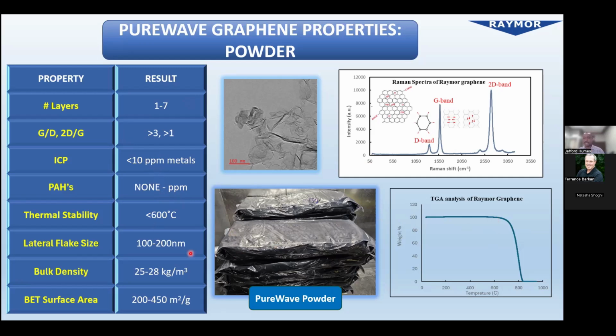Now, the lateral flake size is a bit on the smaller end compared to some other techniques, between 100 to 200 nanometers, but the bulk density is very good, 28 kilograms per cubic meter, with a BET surface area up to 450 meters squared per gram.